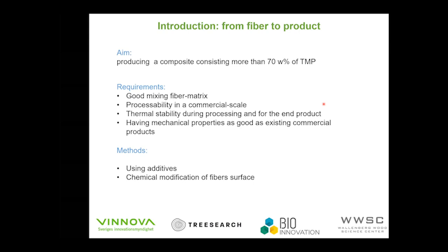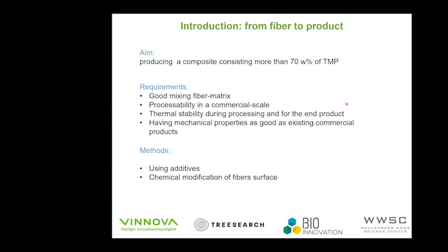So at the end of my PhD, I'm aiming for the kilo scale, but now we are talking about ton scale at the end. My composite should be thermally stable during processing, for example the extrusion, or in the end product also. And at the end, having very good mechanical properties, at least as good as existing commercial products. So we have used mainly two methods: firstly using additives, and the second one, chemical modification of the fiber surface.